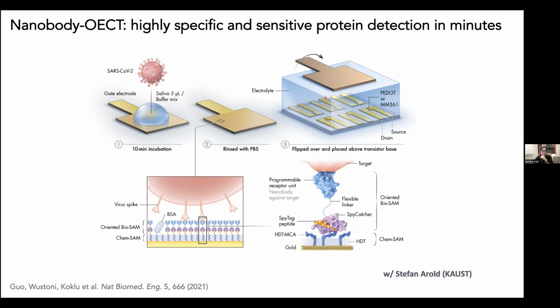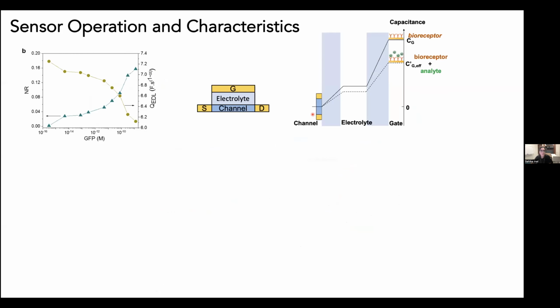And this could be simply a salt solution like sodium chloride, even 0.1 molar concentrations, then we go ahead and start measuring the transistor characteristics. Now, how do these devices work and what do we rely on? We rely on the fact that once the binding of the protein takes place, there's a change in the impedance characteristics of the gold electrode. The capacitance of our gate electrode decreases continuously as more of the protein binds to the surface. And initially we are using a GFP nanobody, green fluorescent protein nanobody, as a model system, and GFP as the target to characterize the performance of these devices.